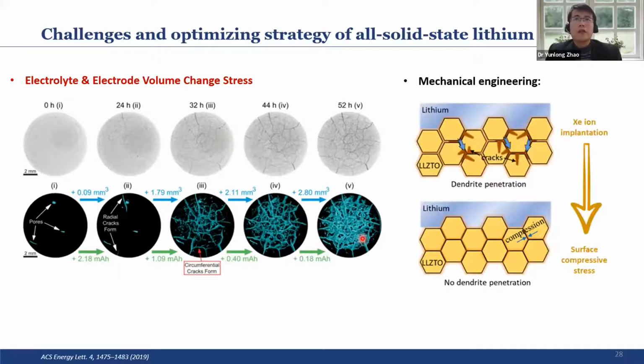There are also different kinds of strategies, and one strategy is mechanical engineering. This is our recent work that was just submitted. We can use an ion implantation method to create some pre-strain and make a pre-strained solid state electrolyte, which can overcome this situation, stop the dendrite growth, and give longer cycling performance.